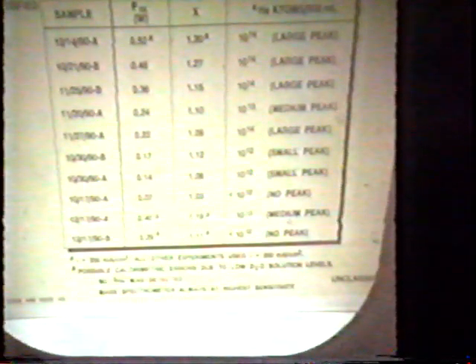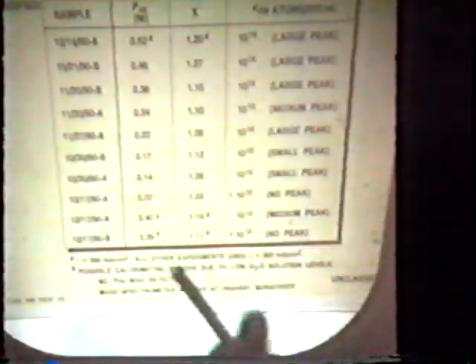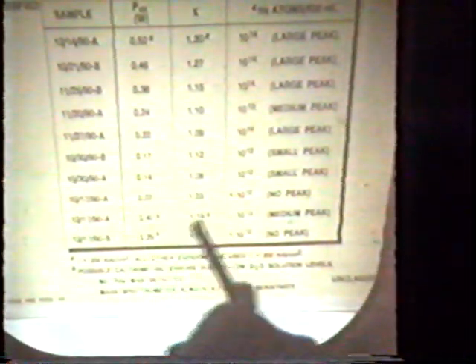There were a couple of samples that we didn't know. The electrolyte level got too low on this sample, so we're not sure about the calorimetry. We didn't find any helium in that one sample. We show the sample, but we realize there's a calorimetric error there because the level got below the palladium. And whenever that happens, recombination becomes a very likely occurrence, so that could very easily be an error. This one is probably okay. We put it down with it because they're both on the same day, but it was probably okay. There's no reason to really throw that calorimetry out in that case.